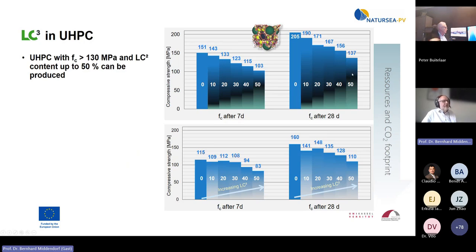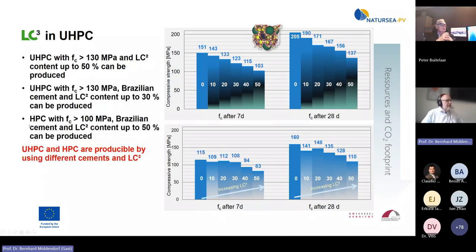Then we have, after 28 days, a strength of 137. And what I have also done, I did not use only a German cement, I used different kinds of cements. Also I used some Brazilian cement just to get ideas of what we can do. Here we used a Brazilian cement, and here 115 megapascal after 7 days, 160 after 28, and with 50% we have 110. And now we have to think whether 110 or 140 is enough to use it as a UHPC.